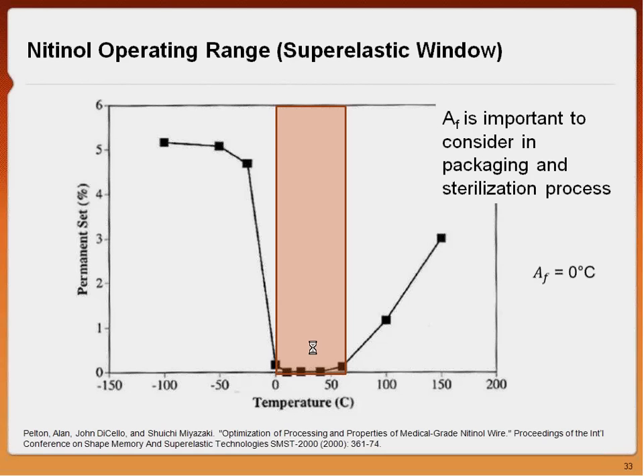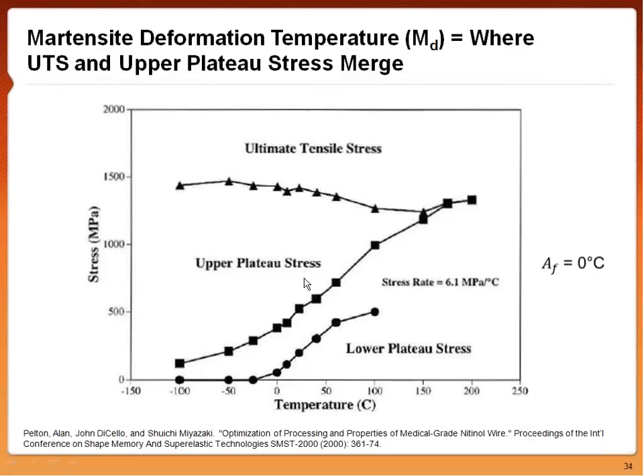And the other thing to consider too, again, is that when you increase your test temperature based on your AF, again, AF is 0 degrees Celsius, you have a linear relationship between your upper stress plateau and your lower stress plateau. And again, at the Martensite deformation temperature, you see that the ultimate tensile strength of your material doesn't really change until you reach this point where we can see that the upper plateau stress is meeting it, which is indicative of our Martensite deformation temperature. So you have to keep in mind that when you reach these high temperatures like that, you have to watch out for how much permanent set is going into your material and how much you're destroying it.